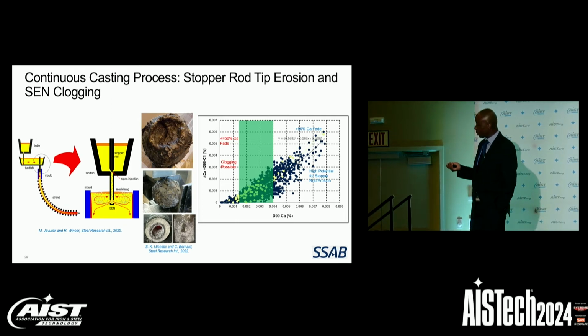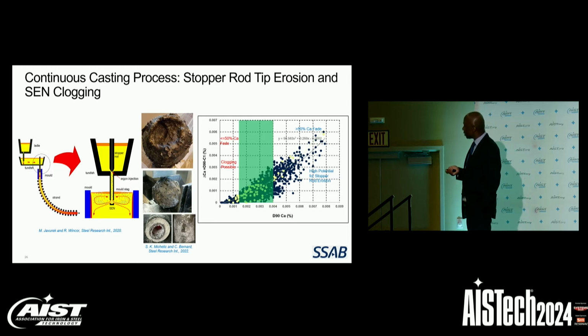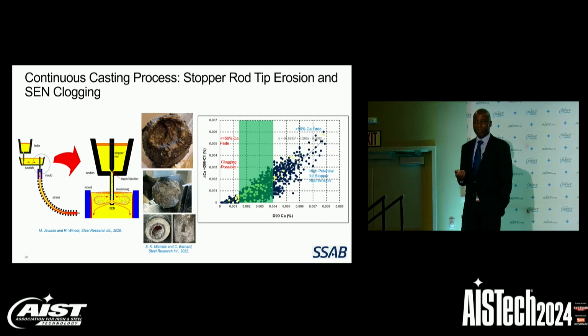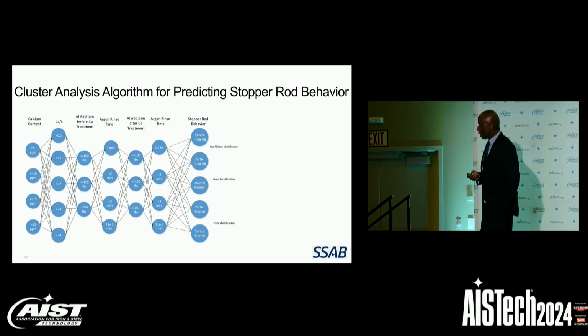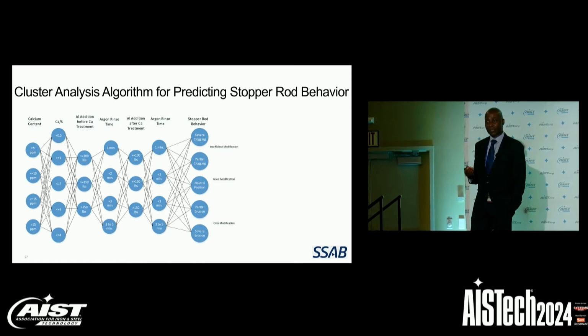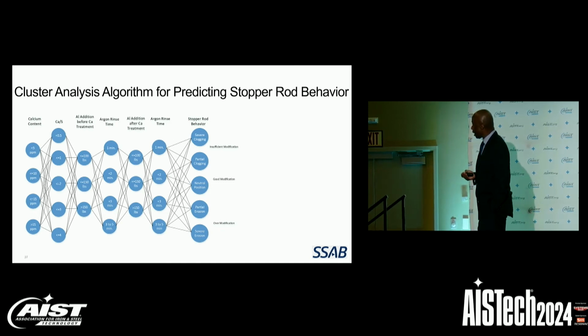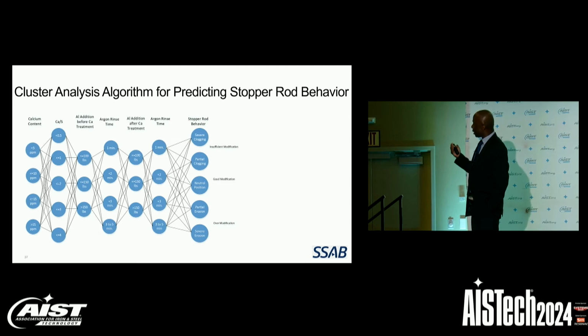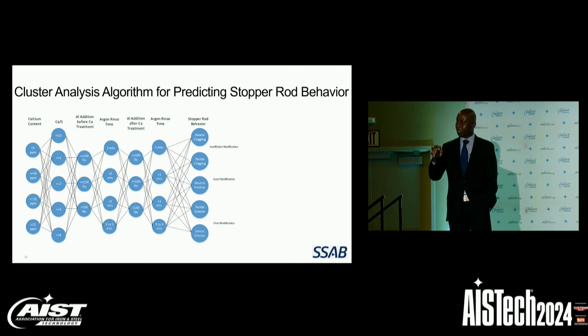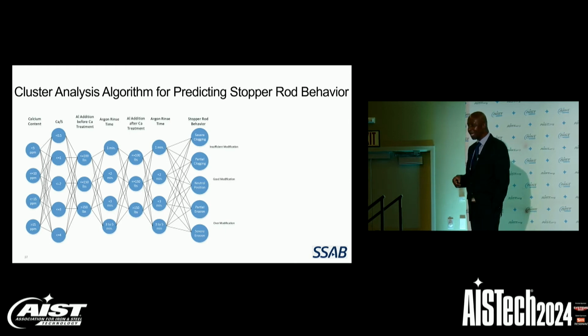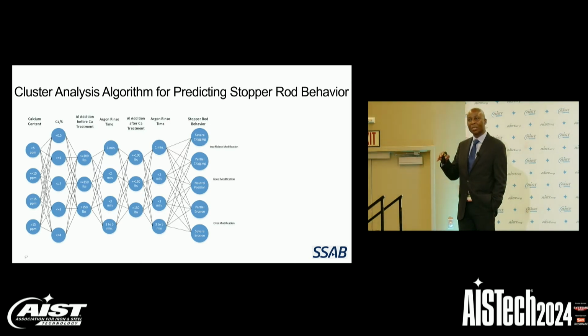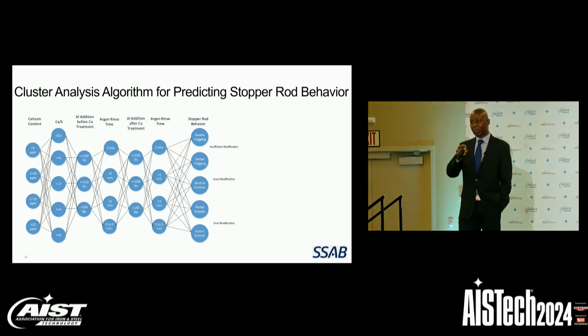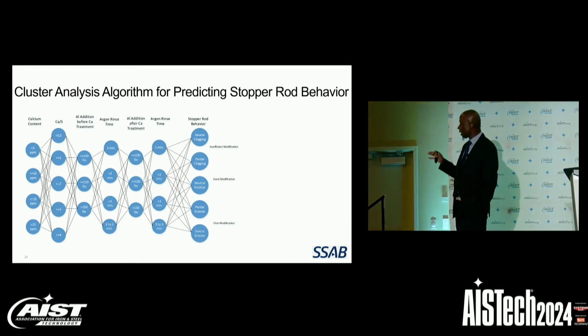I.e., if the calcium content resides to the right of the green zone, there is high potential for stopper rod erosion. And if the calcium content is to the left of the green zone, then there is high potential for SEN clogging. We identified other process variables that can affect stopper rod erosion or SEN clogging. And then we decided to use a cluster analysis algorithm, a type of machine learning algorithm, to predict the stopper rod behavior. So based on historical data, each process variable is classified into clusters with tight boundary conditions. This allows us to identify a combination of process variables that will lead to either stopper rod erosion or SEN clogging.